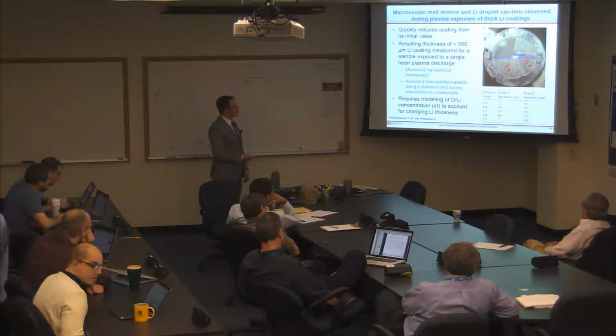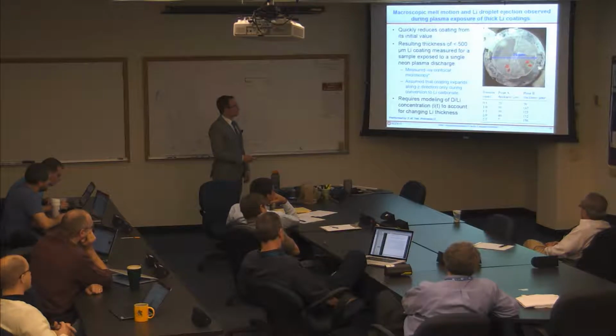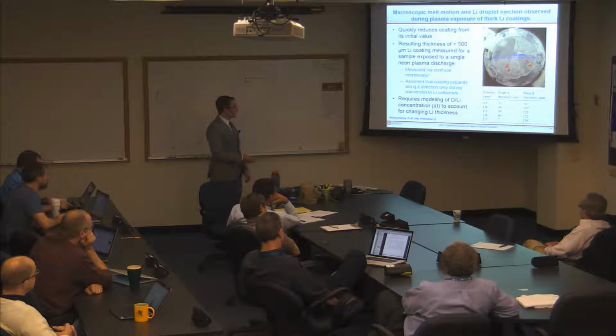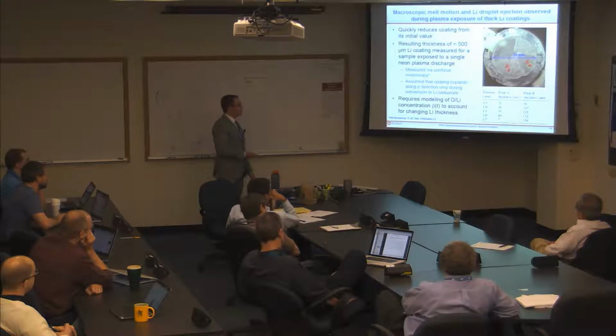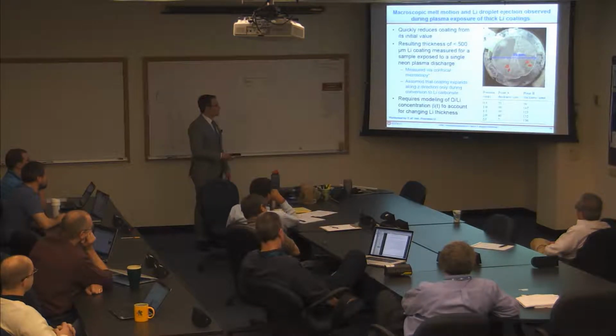And so as you can see, it kind of got everywhere since it was just initially in this little cup right here. And so what I did is I took this one sample that still has lithium on it, and I measured, and then I took it out and I measured what the resulting thickness was as a function of position across the sample. And you use a technique called confocal microscopy, which is an optical microscope technique.